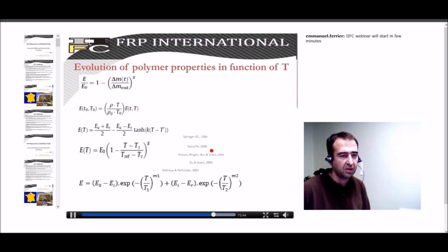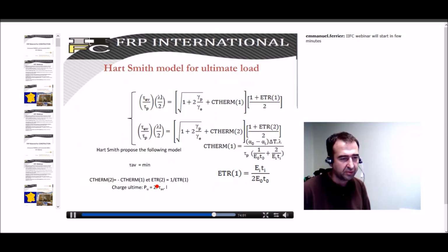We found a lot of models about bond issues in the literature, quite old models. All these models try to introduce temperature in the shear behavior to model the mechanical properties. If we look, for example, at Hart Smith, a researcher coming from aerospace who has worked a lot on bonding problems, he introduced terms in the shear stress distribution due only to thermal effects, and also plastic strain due to local debonding. He calibrated all these constant values depending on the variation in temperature, the difference in the thermal expansion factor and the conductivity of the material.